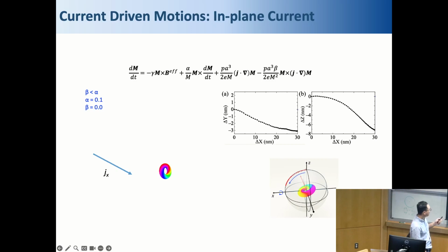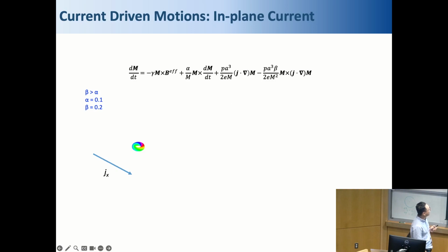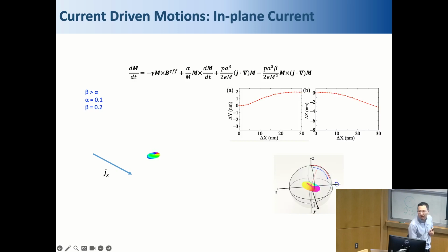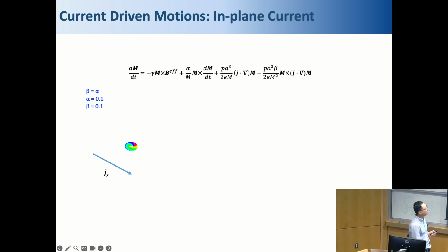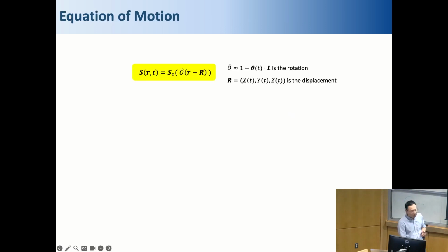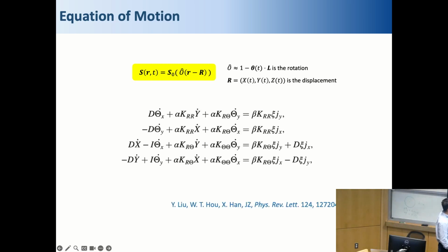Beta is the non-adiabatic spin transfer parameter, alpha is the Gilbert damping. If beta is larger than alpha, we do the same simulation, apply the same current, and it moves in the same longitudinal direction with the same velocity, but opposite transverse velocity and opposite rotation direction. In a very special case with beta equal to alpha, this hopfion moves straight without any Hall effect and no rotation. We also model that in terms of the collective equation of motion. I will just skip that. But finally, we end up with this equation of motion for the hopfion.